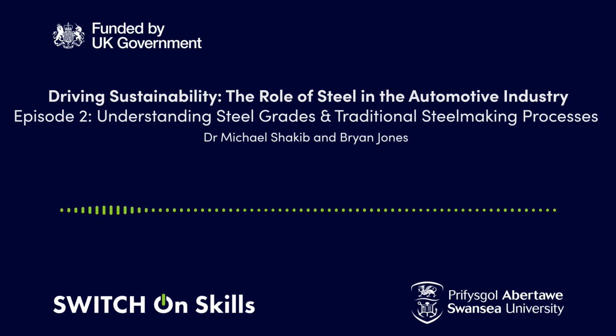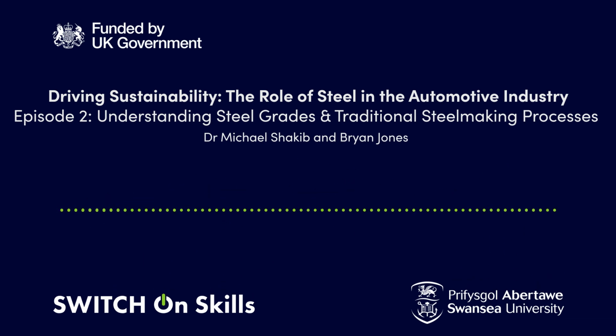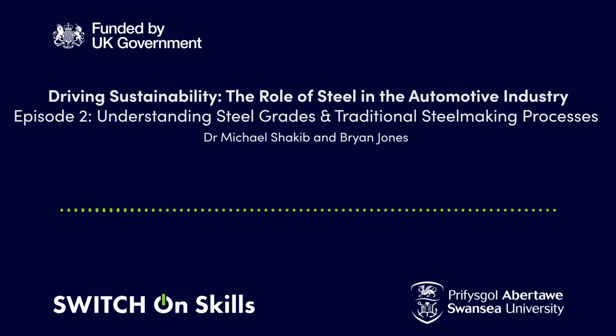I put scrap in first. What's BOS stand for, sorry? That's basic oxygen steelmaking. Okay. So you've got, say, 18-20% of scrap material. So you need less hot metal then to produce your product, using recycled product together with fluxes. And then during that BOS steelmaking process, there's a progressive reduction in the amount of elements that you do not require in your final product.